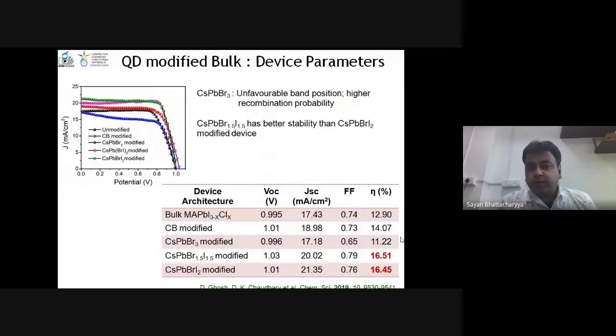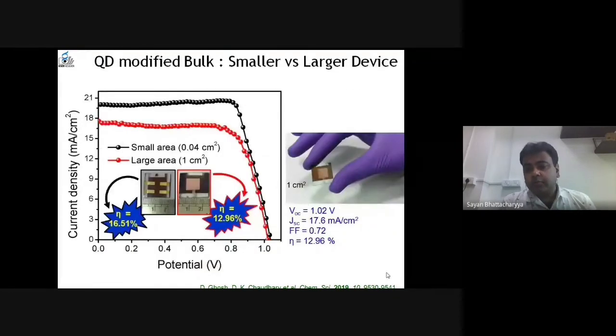Now, these are the final efficiencies. You can see the Br 1.5 and I 1.5, this is around 16.5%. BrI2 is also very similar. It is 16.45. So around 16.5, but this one works better because stability is also an important issue, and this one is more stable than the other one.